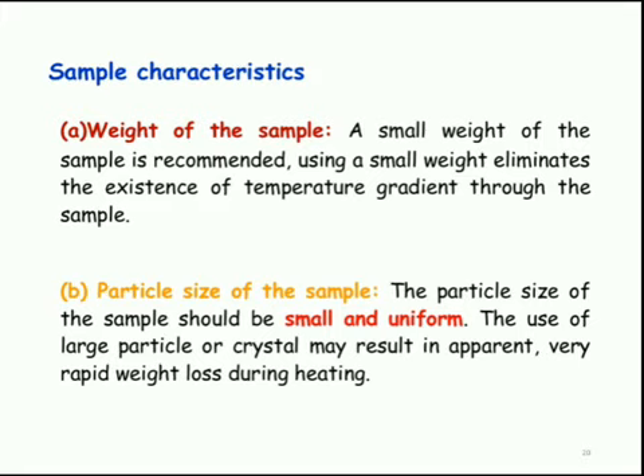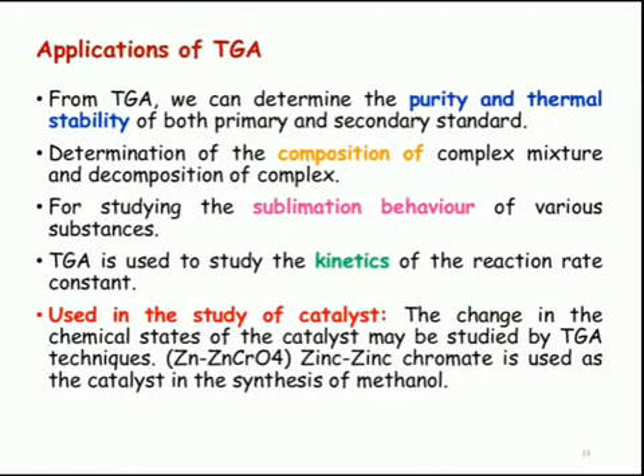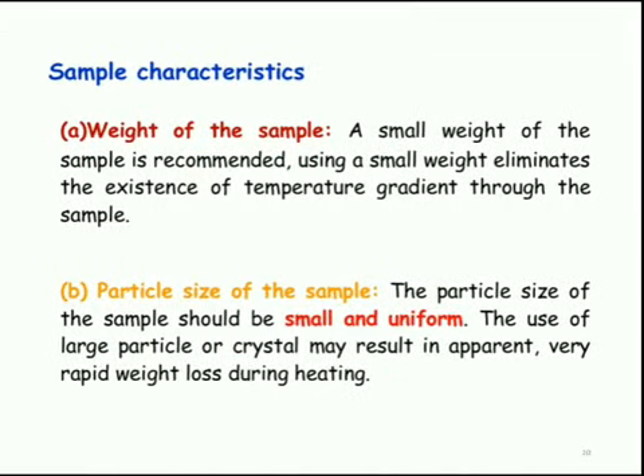When we use a small weight, that eliminates the temperature gradient, that is, the temperature variations through the sample. And the particle size of the sample should be small and uniform. When we use a small and uniform particle size, it increases the accuracy of the measurements. If you use a large particle or crystal, it may result in apparent very rapid weight loss during heating. So we can avoid this if we use small and uniform particle sizes.